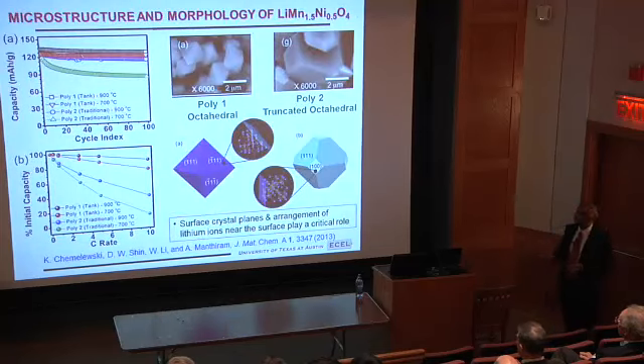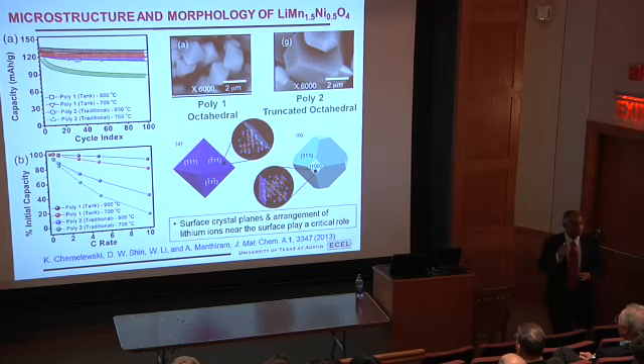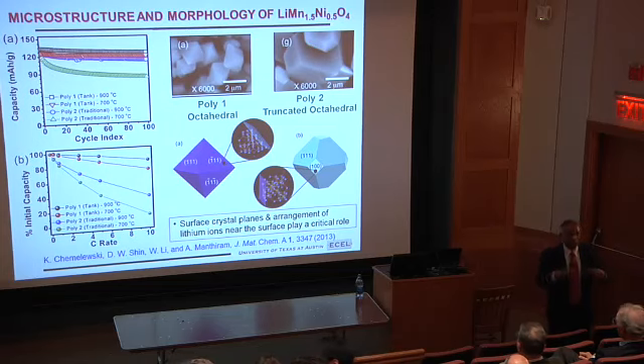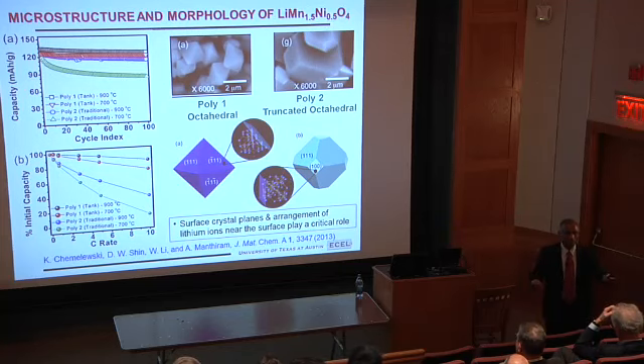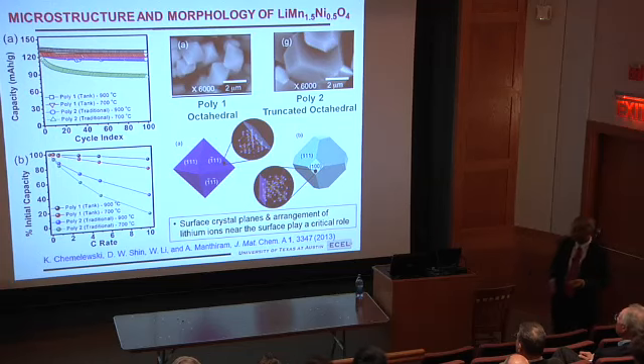We also find when you have crystals like perfect octahedra, like this, with 111 planes on the surface, they perform much better than crystals in which you have truncated 100 planes and then a lot of 111 planes. So surface morphology, surface plane is very critical for how the lithium transfer or the manganese dissolution, metal dissolution occurs in these materials. So it's not only that you identify the specific material, you have to also make them in such a way that you have the right surface, so that they do not react too much or they do not dissolve a lot of metal into solution.